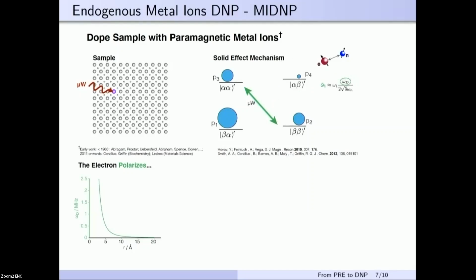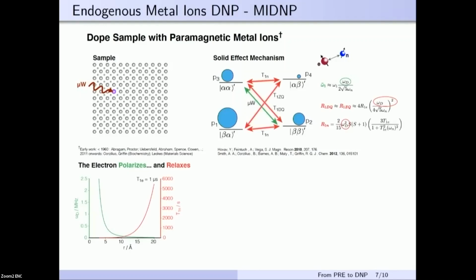Then at the same time, we have to consider what is trying to counteract our effort to saturate this transition, and it is the relaxation. Here comes the fun part, because these are rigid solids where there are not many relaxation mechanisms present. The main source of relaxation is actually the metal ion that we introduce for polarizing. So it has this double function: it gives us the polarization and it inhibits us from getting more polarization. And here again, the same story is true. The further away we are from the polarizing agent, the weaker the interaction, the longer the relaxation time, the more time we have to get the enhancement to these nuclei.